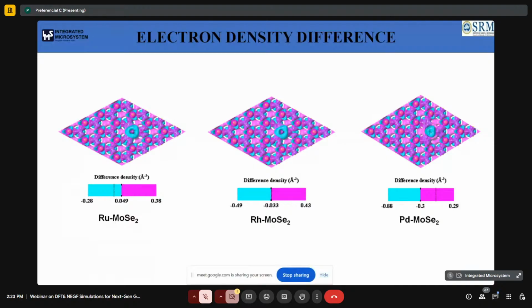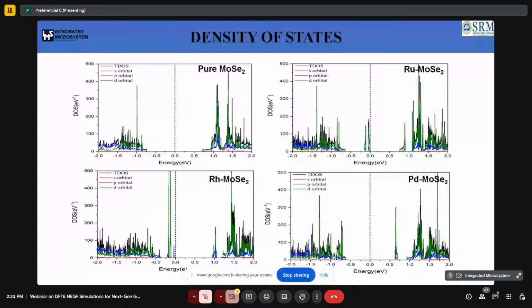Coming to the density of states, impurity peaks appear very close to the Fermi energy level, and this is because of the incorporation of this dopant. All these modifications mainly come from the d orbital hybridization, which is predominantly observed in the density of states analysis. From the density of states analysis, we again validate that new impurity energy states are arising close to the Fermi energy level, and this matches well with the band structure analysis, where new energy states are also created close to the Fermi energy level.